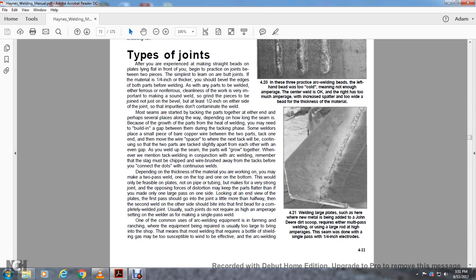Depending on the thickness of the material you are working on, you may make two-pass welds, on the top of the joint and on the bottom. This works only with fusible plates, not on piping and tubing, but it makes a very strong joint, with the opposing force. The distortion may keep the part flatter than if you made only one large pass on one side. Looking at the end view of the plates, the first pass should go into the joint a little bit more than halfway. Then a second weld on the other side of the joint should bite into the first bead for a completely welded joint. Usually such a joint does not require a higher amperage setting of the welder than making a single pass weld.